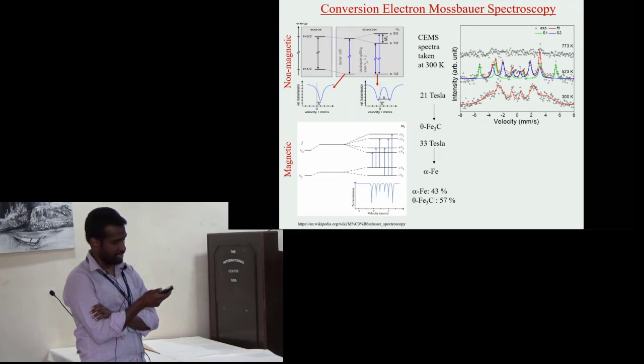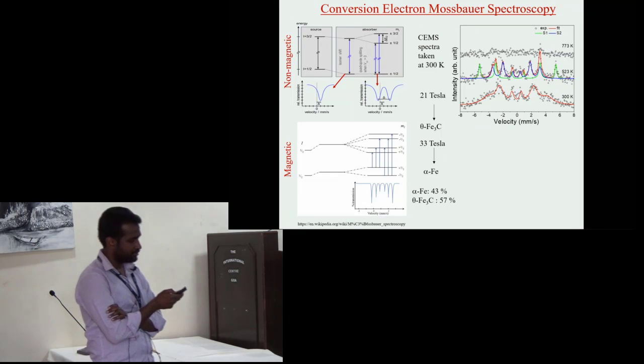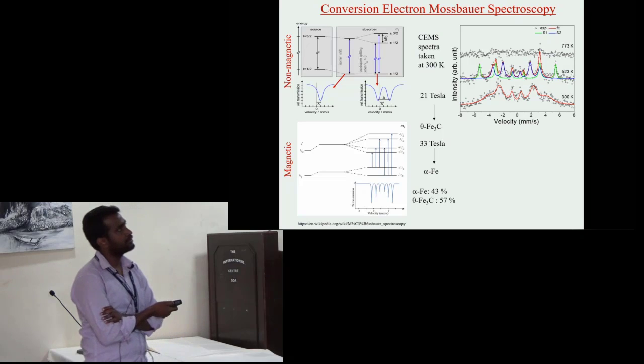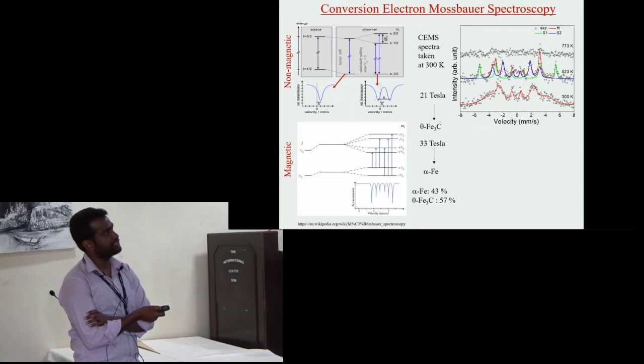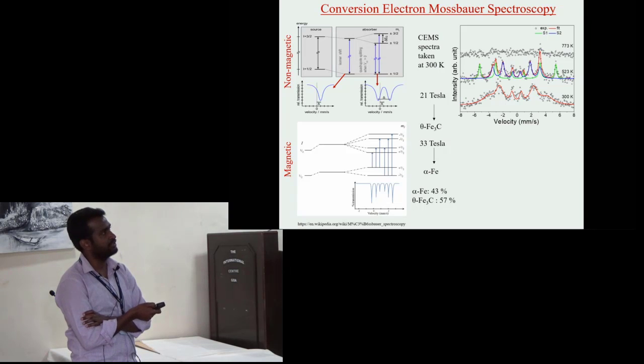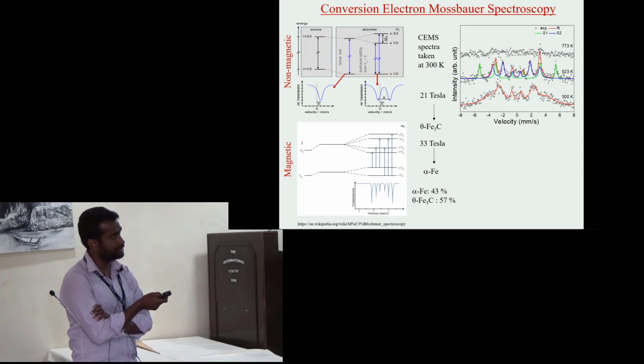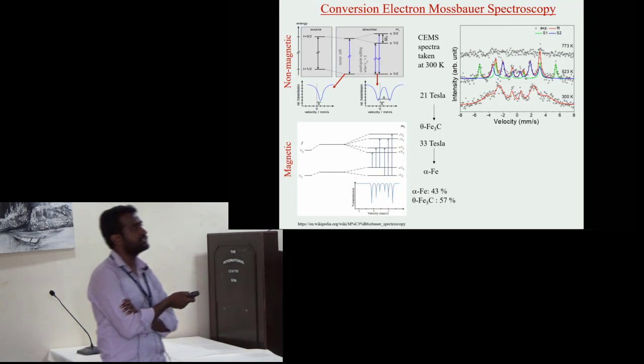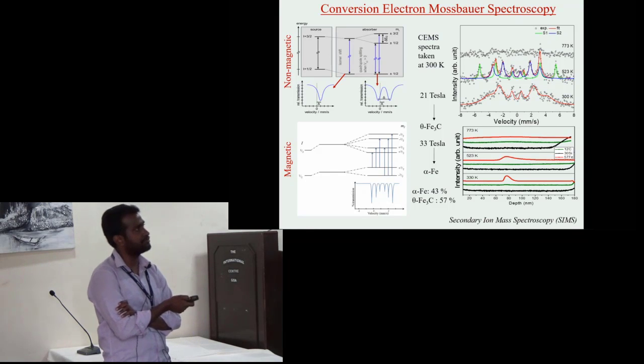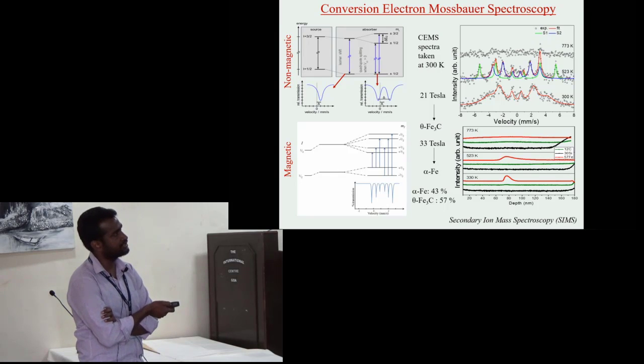This is for our sample. At room temperature there is broadening in these resonance lines that shows the sample is amorphous, and such spectra can be fitted using one hyperfine field of 26 tesla. This spectra we have fitted using two hyperfine fields of 21 and 33 tesla that is related with Fe3C and Fe.